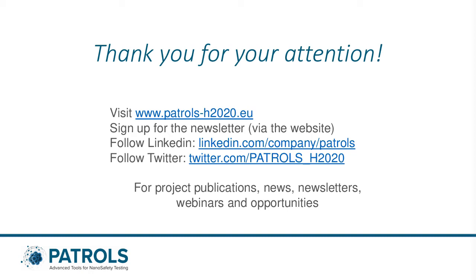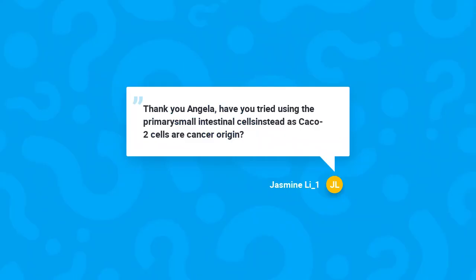I think so too. What we have seen recently, and it is an accepted publication, which hopefully soon becomes available, is that we have compared different in vitro models of the intestine: proliferating monocultures, then the epithelial co-cultures, and then the triple cultures together with the THP1 cells. We have only seen effects of different types of nanoparticles in the proliferating monocultures. But once you have an epithelial co-culture with differentiated cells, a dense cell layer, the reaction at least at very obvious or easy to detect endpoints is almost zero. So I think you would really have to go to very sensitive endpoints, like the proteomics or transcriptomics level, to still see something there.